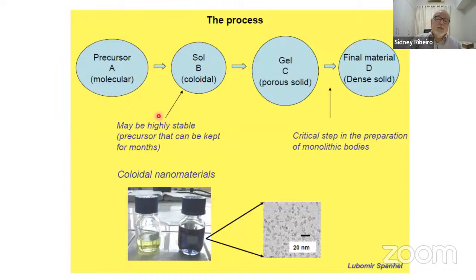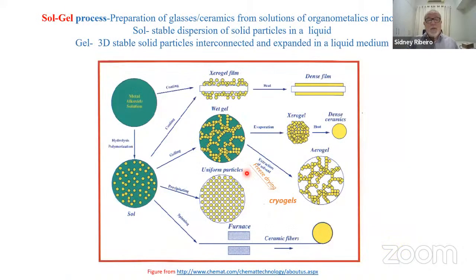So the process is summarized here. We have a molecular precursor that we hydrolyze in order to obtain colloidal particles with controlled properties and sizes, and this we call a sol. Then by removing the solvent, we can have a gel. It is a porous, rigid solid that we can densify or not in order to obtain a dense solid. In terms of making macroscopic materials, this is the critical step, because we need to control the material in order not to have cracks, for example. The colloidal sols are very stable. We can keep them for months. So we have a collection of nanoparticles in a liquid solution.